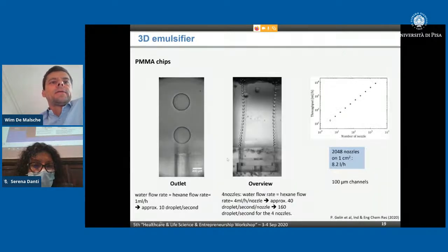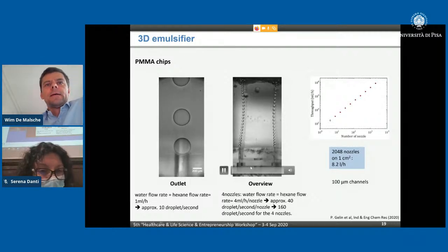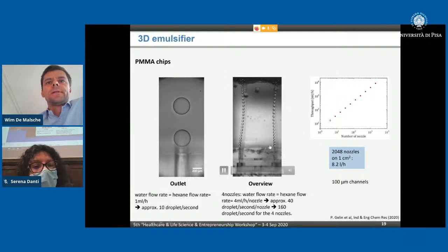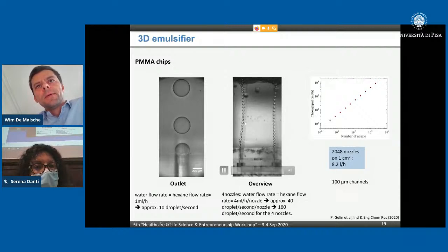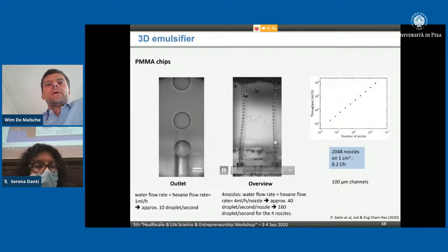And here, outside of the PMMA chips, you see droplets being formed. Here again, we have 10 droplets per second, more or less. Here we have an array with 4 nozzles. We can only focus on 2 in the image, and so we also have 2 behind. You can see the droplets there, and we are making monodispersed droplets here. All of them, we can collect them.